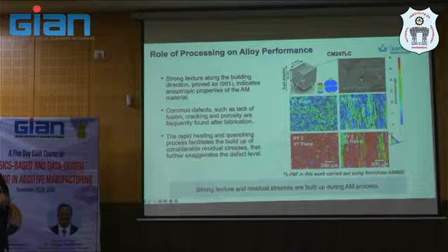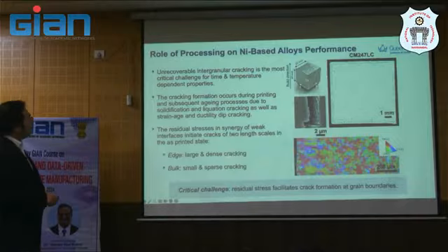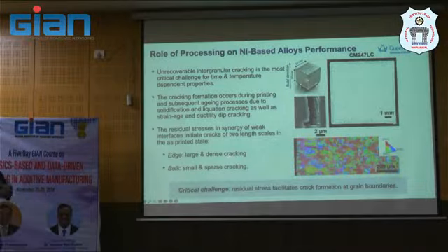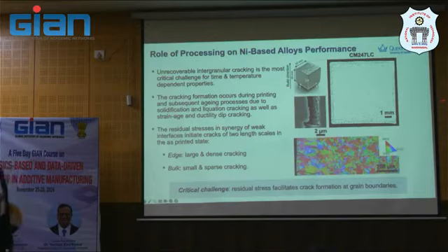Based on observation, strong texture and residual stress build up during the process. So we printed this nickel-based superalloy under conditions we believed were optimum, but you still find a lot of cracks here, which I will show you later.